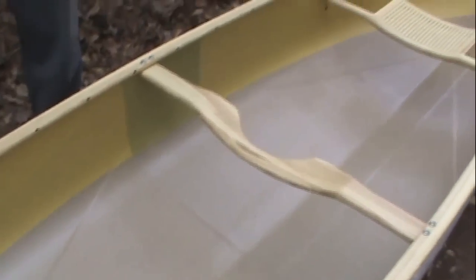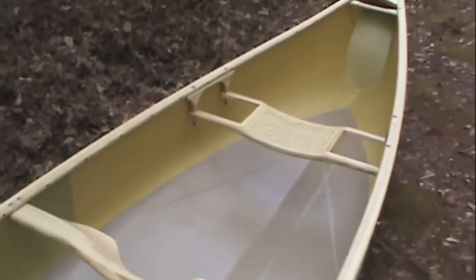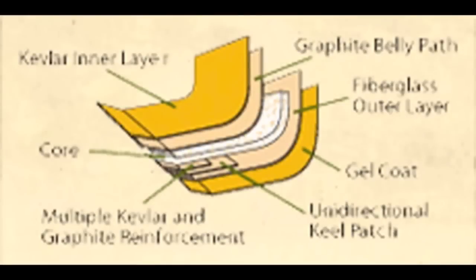This boat is actually a hybrid layup. It starts off with an outside gel coat, which is designed basically to protect against scratches and that kind of thing, and a layer of fiberglass. The reason we use fiberglass in that position is it does give some stiffness to the boat, but it also bonds better to the gel coat and is actually easier to repair if the unforeseen happens.